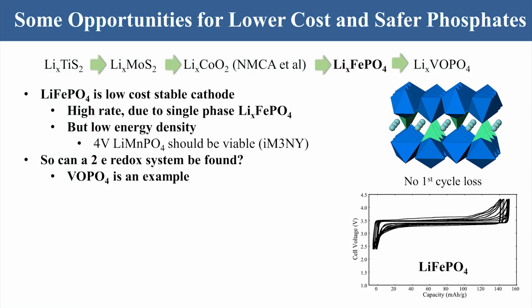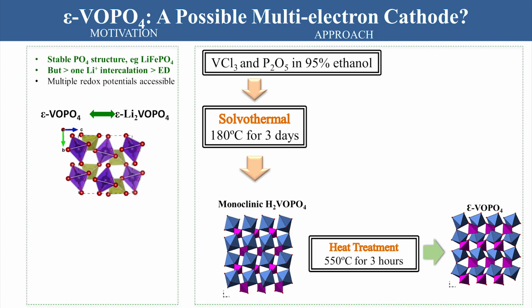across the street from where we are is using a variation of lithium manganese phosphate. That's 4 volts versus the 3 volts of iron phosphate. So we looked at vanadium, and if you remember back to your freshman chemistry days, vanadium can go from 5+ to 4+ to 3+. So we can easily go from 5+ to 3+. So we can do a 2-electron redox process and put 2 lithium ions in there.